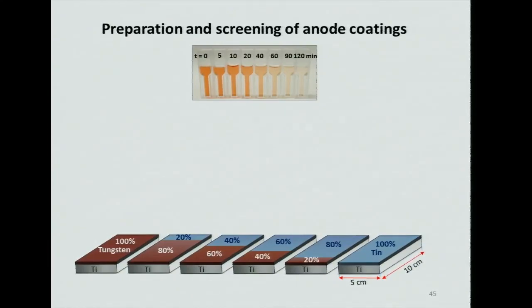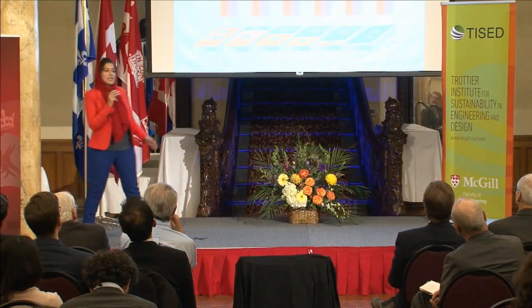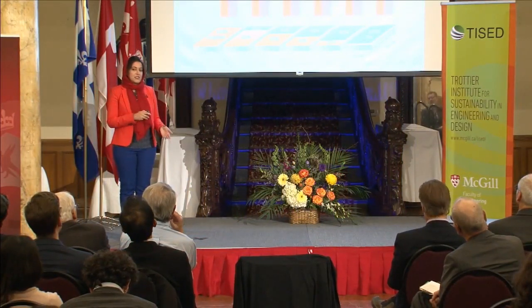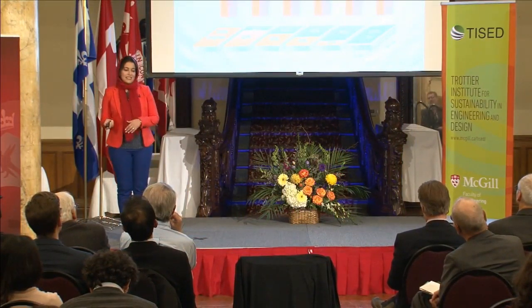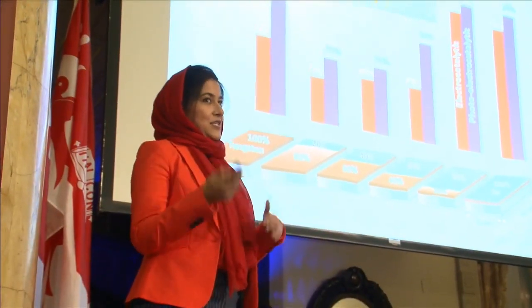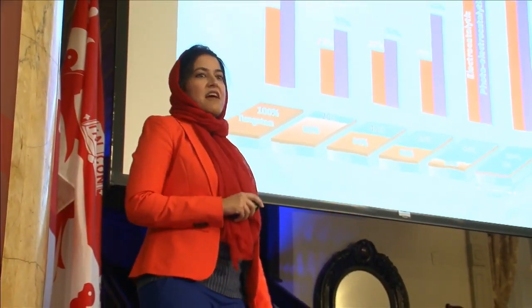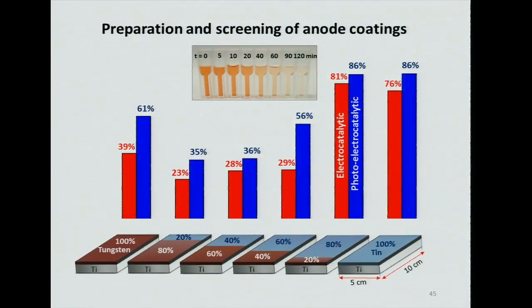The results for the removal of phenol red by using 2 processes, electrocatalysis, which is the use of electricity, and photoelectrocatalysis, which is the use of UV and electricity at the same time, are shown as graph bars. And as you can see, the coating composition with 80% tin oxide and 20% tungsten oxide exhibited the highest degradation percentage for removal of phenol red. So this coating composition was selected as our best candidate for further experiments.